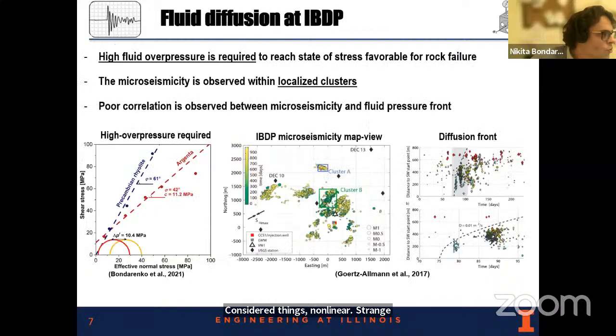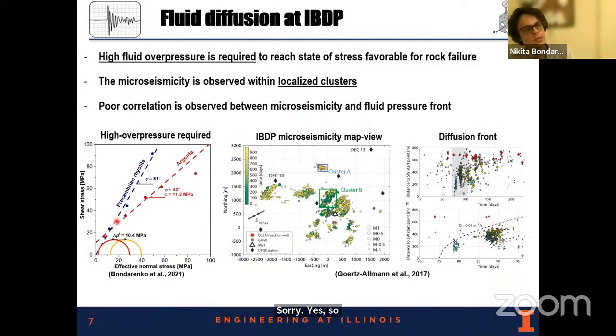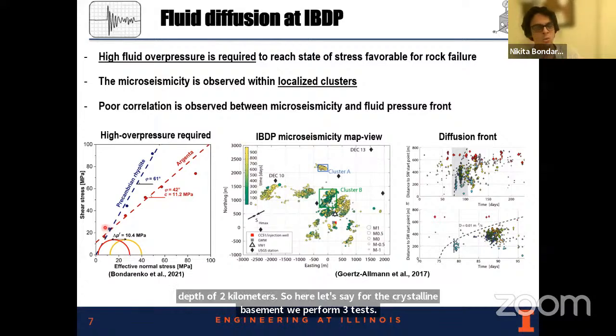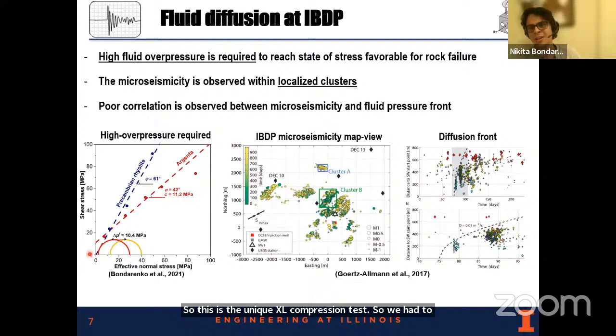Sorry. Yes, so this is our experimental data. Definitely, if we want to consider some non-linearities, it would be just in the area of low stresses. At the same time, it's challenging to characterize this material just because it has pre-existing fractures. We have a very limited number of cores extracted from a depth of 2 kilometers. For the crystalline basement, we performed 3 tests. This is the uniaxial compression test. To estimate strength in this area, we would have to perform triaxial extension or uniaxial extension tests, which is challenging to perform.